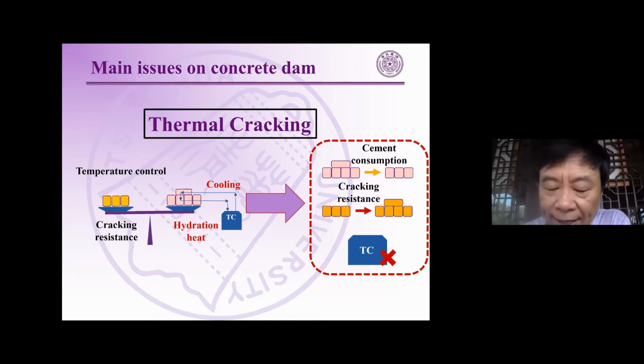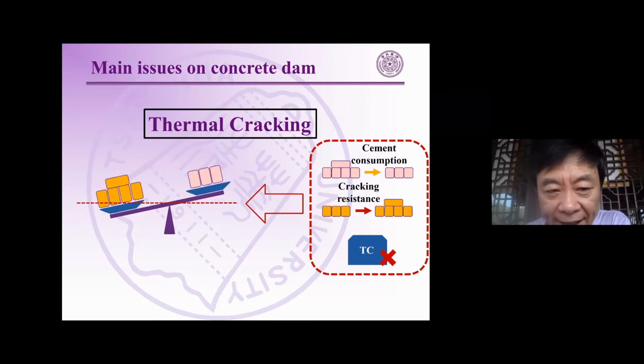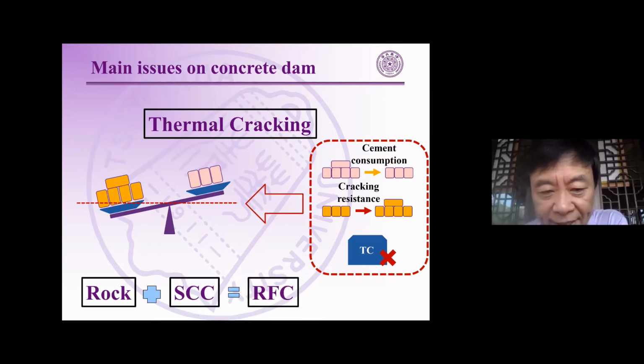So we have to develop a new method to lessen the cement consumption, and at the same time not allow the cracking resistance of the concrete to reduce. So we have to develop a new method without cooling pipe or other temperature control measures, to let the cracking resistance of the concrete be greater than the thermal stress. And then we developed a new method that we call rock-filled concrete.